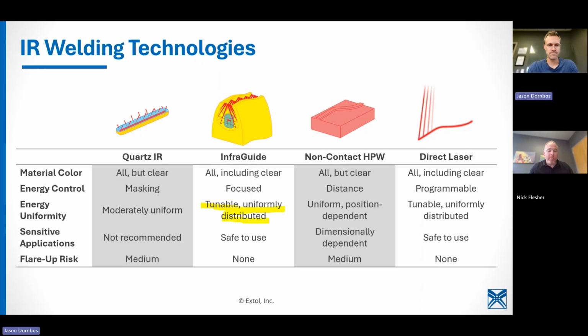Tunable, uniformly distributed. If it's not uniform right out of the box, we've even taken vibe welded parts that had to be converted, and the customer said we can't change our mold, and had really fat corners, almost double the width. And we just turned all the other emitters down, and got completely uniform, even though the thermal mass was not the same.